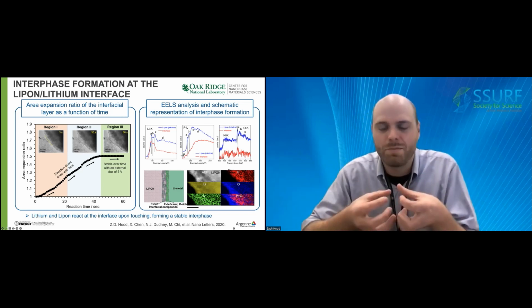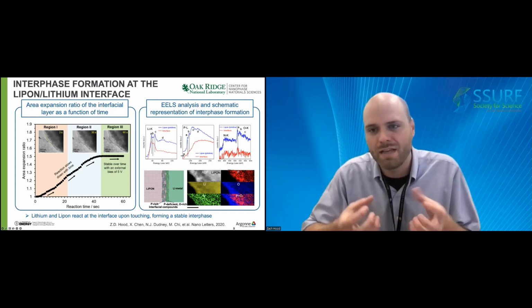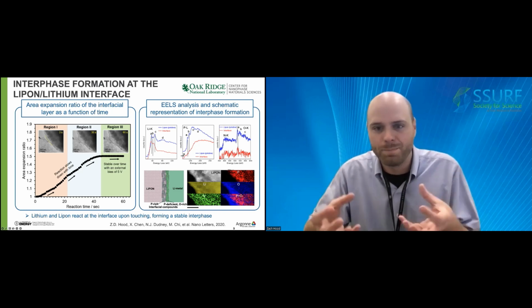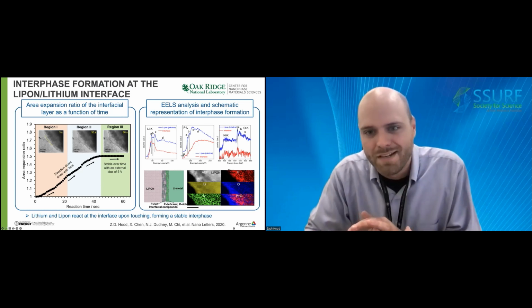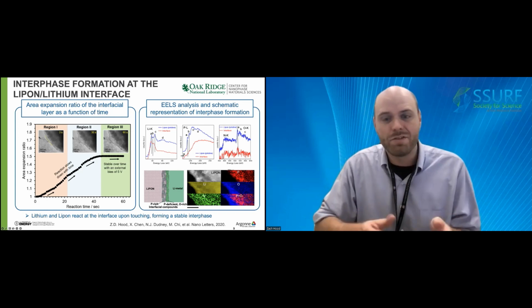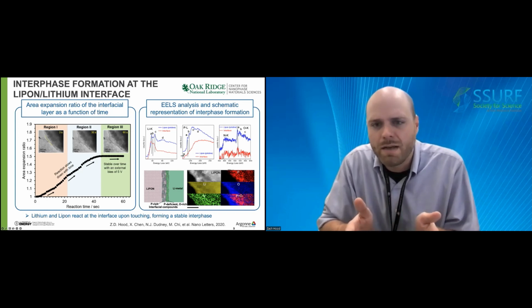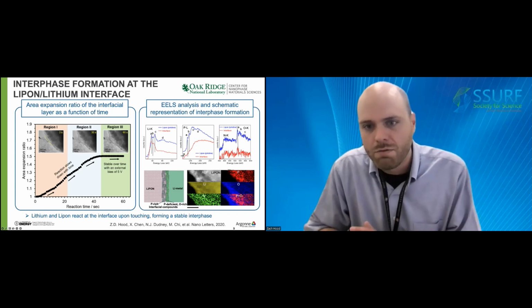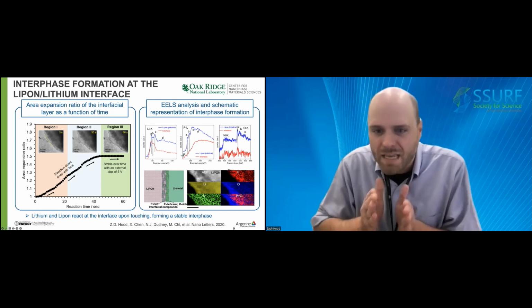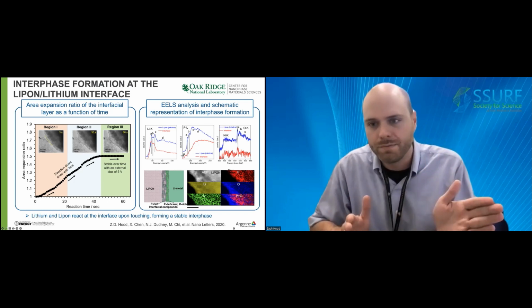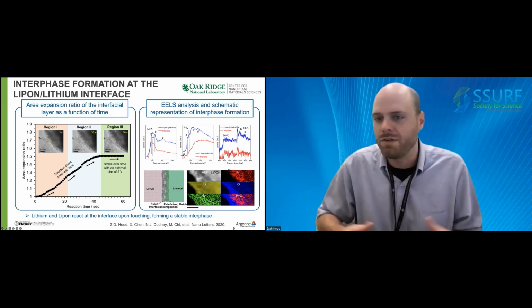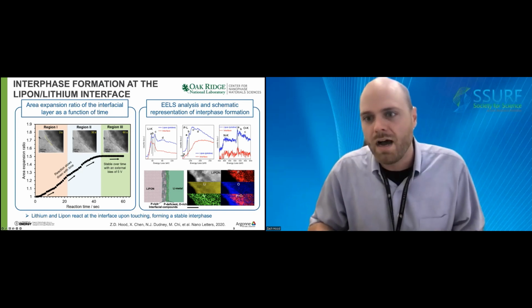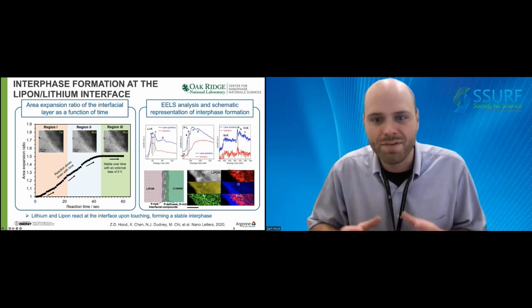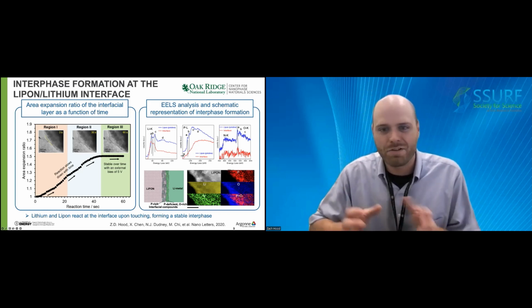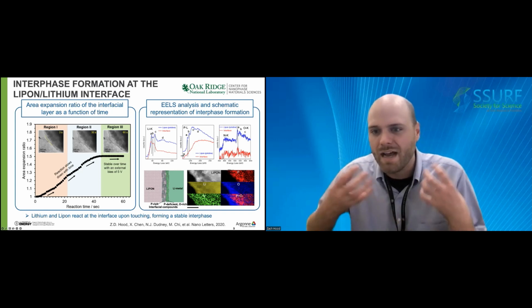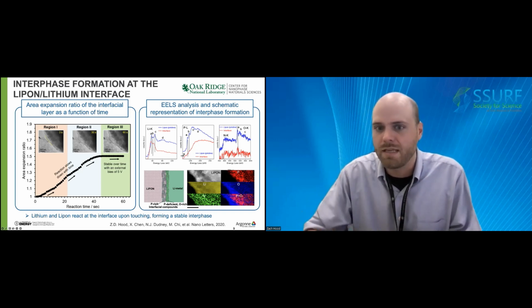First, when LiPON is contacted with lithium metal, an interface forms as a result of LiPON decomposition at the very surface of that LiPON. Second, the thickness of the interface is limited to around 50 nanometers and does not grow with time, even after an external bias of 5 volts, which means that this interface layer is effectively stabilizing LiPON with lithium metal and may contribute to the long life of LiPON being used in next generation all solid state lithium metal batteries. So information provided in this work fills the knowledge gap regarding the electrochemical stability window of LiPON and its high stability and cyclability in all solid state batteries.